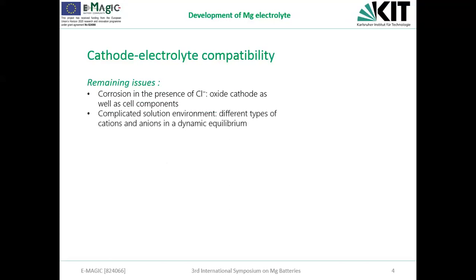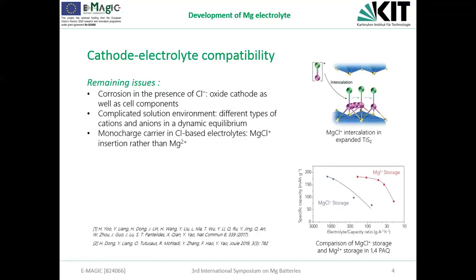On the other hand, we also have a complicated solution environment with dynamic equilibrium in the chlorine-based electrolyte. As shown before, we have a couple of these magnesium chloride cluster species, and this monocharge carrier has the possibility even to intercalate into the system as a whole, rather than the double charge carrier. And as reported before, for the magnesium chloride storage, if we have this scenario, then we might need more electrolyte if we want to achieve the same specific capacity as in the case of magnesium ion storage. So there's an urgent need to develop a chlorine-free simple salt electrolyte.